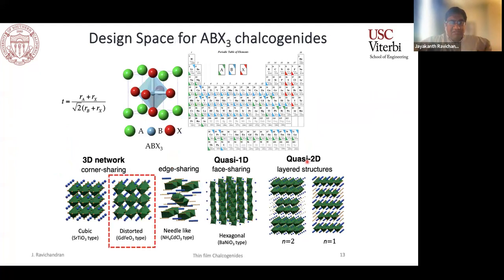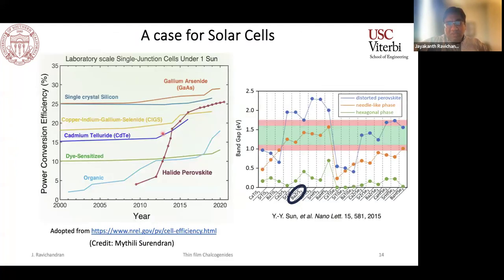The other type of interest is in these distorted perovskite-type compositions. And the big motivator for this class of materials was the spectacular rise in the power conversion efficiency of the halide perovskites, which prompted people to think, if there is something special about this perovskite structure, where halides tend to have a lot of stability issues, perhaps chalcogenide perovskites could act as a more stable version of it, but still give you some interesting optical properties for photovoltaics or other applications.